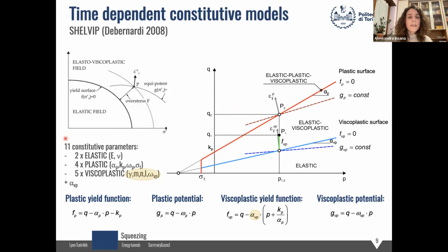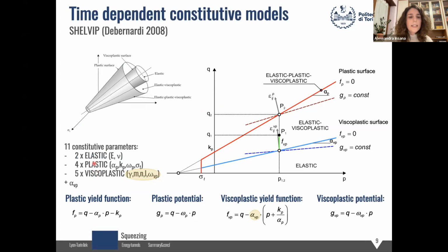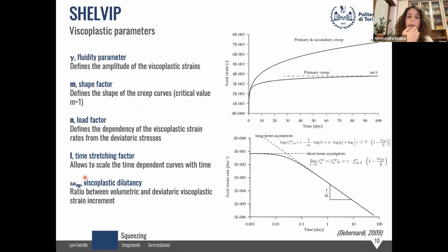So this model is constituted by 11 parameters. So 2 are elastic, 4 are plastic, and these ones can be evaluated according to classic laboratory tests, for example, triaxial tests, and then 5 viscoplastic parameters. And then we have the state parameter alpha_VP that defines the slope of the viscoplastic surface, so the onset of viscoplastic strains. Now we will focus on the viscoplastic parameters.